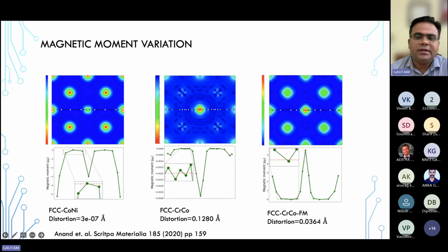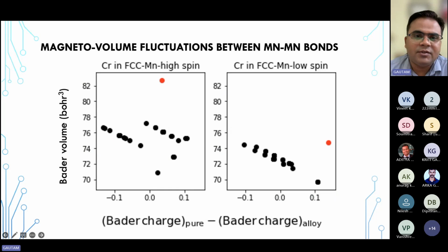When we carried out the ferromagnetic case where we constrained it, which is not the ground state of the system, you can see that these fluctuations basically disappear. So what happens with the manganese, where this is happening? In some cases, when we find high magnetic moment, we are finding significant distortion, while in low magnetic moment, we are finding limited distortion.